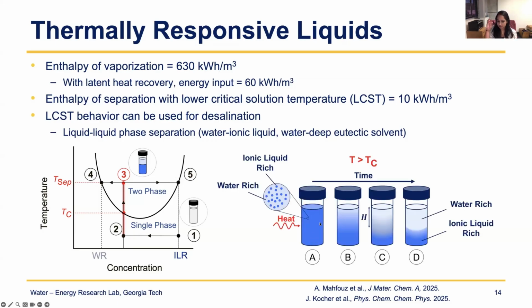So we've done some work to study microscopically what's happening. It behaves almost like a colloidal mixture, where first small particles or droplets of one phase form within the second phase. Then as you keep increasing the temperature by providing heat, the small droplets will start to coalesce. Once they coalesce, they form larger droplets, and then you start to form two macroscopic phases.